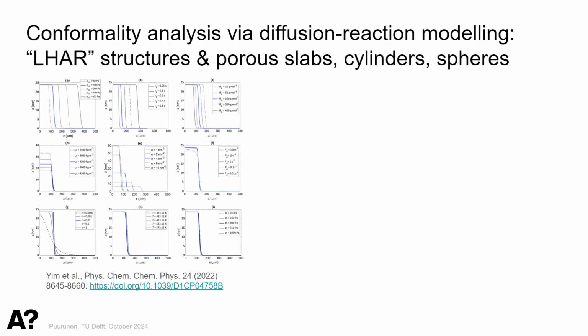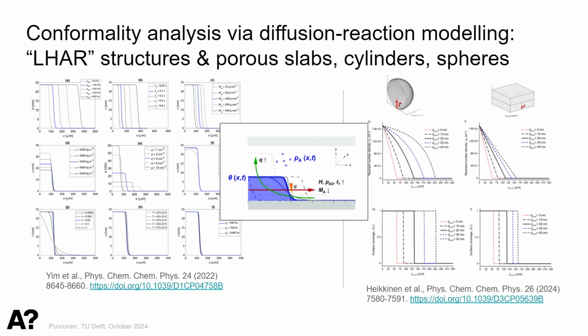And because it's actually quite complex, at least to me and my students, to think how changing these parameters will affect the penetration depth, we have a pure simulation paper out where you can much more easily vary these parameters than experimentally, and another one has just been accepted. I know it from yesterday, in the same journal, and also then similar things for those spheres. I could summarize it here: the coating goes deeper the higher our channel height is when we are in the Knudsen diffusion regime, and the higher the partial pressure, and the higher the exposure time, and the lighter the reactant is.